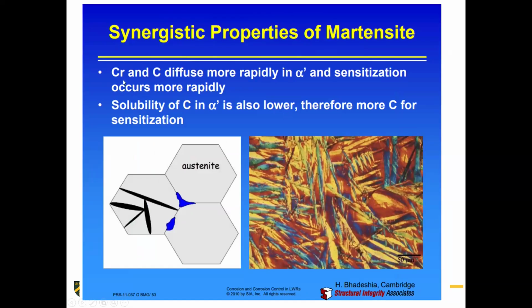So what does that end up looking like? Well, some of the reasons for this is chromium and carbon diffuse much more rapidly through martensite, and sensitization occurs more rapidly. Again, that sensitization reaction is going to be the formation of those chromium carbides at the grain boundaries. And so if you form martensite, it essentially ends up going much quicker through it. And so you can end up kicking off that sensitization much more easily. The solubility of carbon in martensite is also lower, and therefore carbon is more available for this reaction, as well as sensitization.